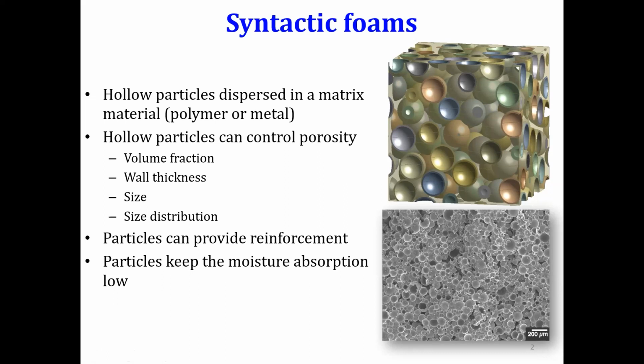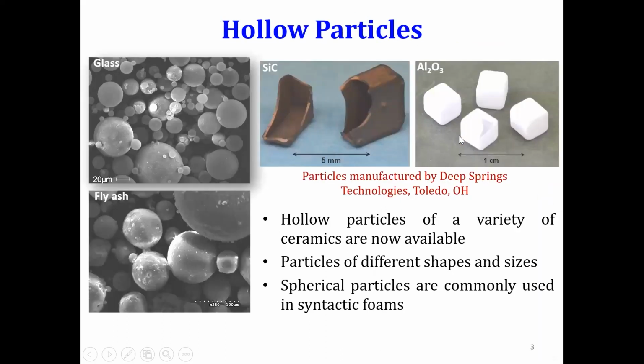So this is the area wherein we have a wide range of property modulation. It need not be only volume fraction or weight fraction based, but for the same volume fraction based on the density, which in turn is governed by the wall thickness of these hollow micro balloons. And that's how these are very beneficial and are being used from aerospace, automobile, and marine applications, and similar systems. Naturally, there are fly ash particles available, which one can utilize to prepare these syntactic foams, or else there are artificially manufactured particles as well.